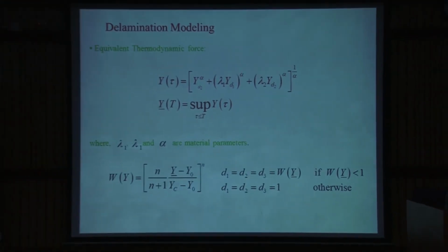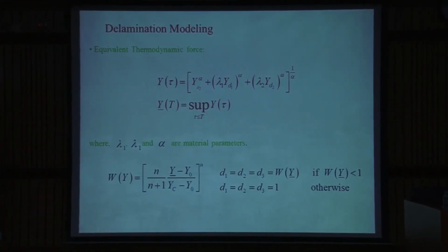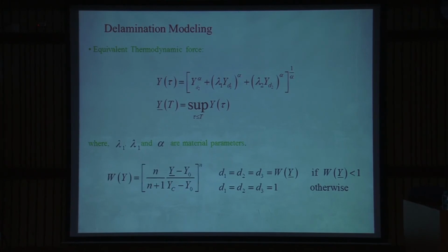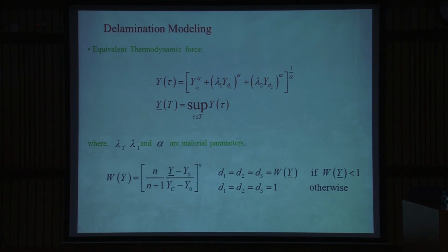For the propagation, you are talking about 3 modes, and I don't want to do each mode one by one. So what is done is that you define equivalent thermodynamic forces where you have all the 3 modes. This thermodynamic force is nothing but an attempt to capture the mixed mode failure. Whatever is written here is just a modified form of the mixed mode fracture of the delamination. Depending on that, you will have lambda 1, lambda 2, alpha, and these parameters, depending on the strain energy you get in mixed mode failure. You do a parameter fitting and then you can get these material parameters.